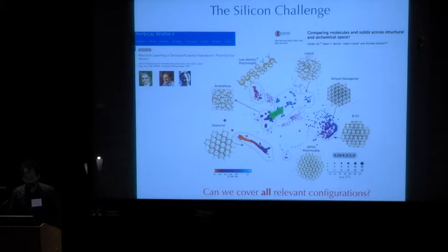Let me draw your attention to these two different groups. These are liquid snapshots, and these are amorphous snapshots. Amorphous silicon is a technological material for sensors. And in fact, the way I made this map, this is a multidimensional scaling map using the SOAP kernel that I introduced. And what that tells you is that this is a very good sign. It actually separates liquid structures from amorphous structures structurally without any dynamics. And that's new physics already, because people, as we heard yesterday, don't know how to think of an amorphous and a liquid structure independently.